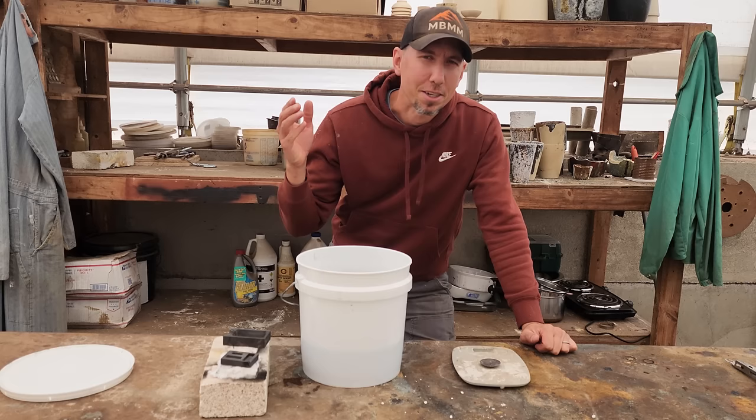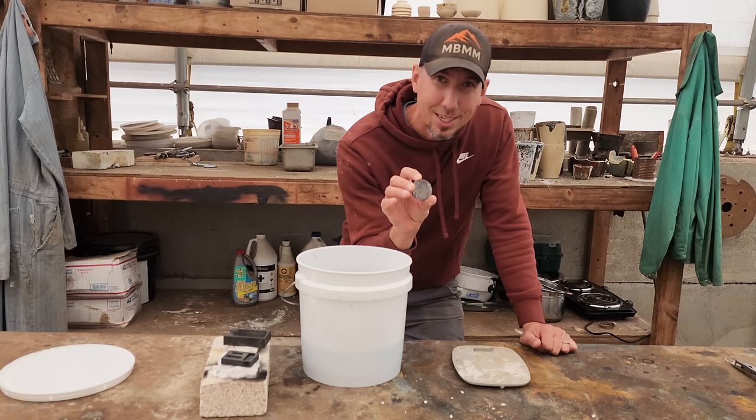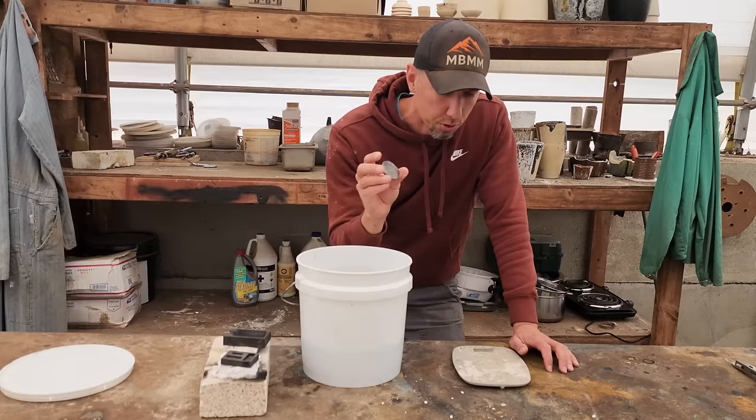All right, guys, well, let's continue to fumble our way through this. It's been the next day. A couple things I want to show you. I ended up with this silver button here out of the cupelling furnace. I tried to shine it up with a little HCl. That was a mistake because it turned the surface a dull gray color, because I think it made silver chloride on the surface. So don't use HCl to clean up your silver.